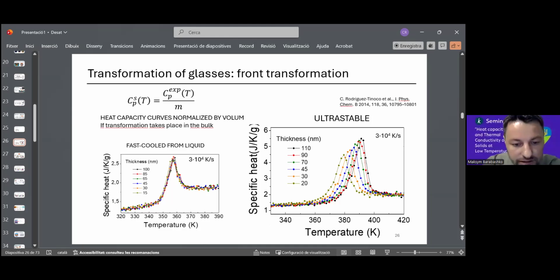Okay, it's glass transitions, and we see the difference for fast cooled and ultrastable glasses. For fast cooled, this temperature is the same for all samples, and for ultrastable, we can see some shift depending on the thickness of these glasses.